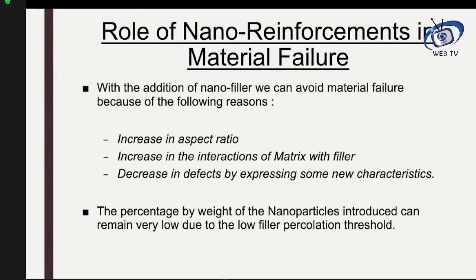At the interface, if there is a greater strength or greater bonding between the matrix and the reinforcement, then we can say that the strength of the material will be higher. A decrease in defects is also expected in these nanocomposites due to the addition of the nano reinforcement. So a decrease in defects also produces enhanced properties of these materials.